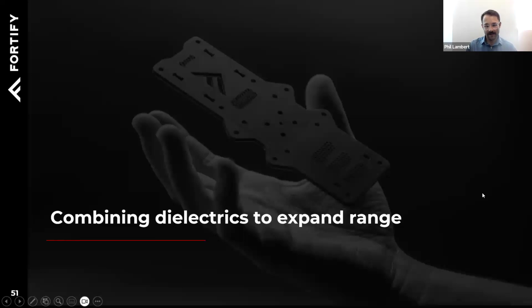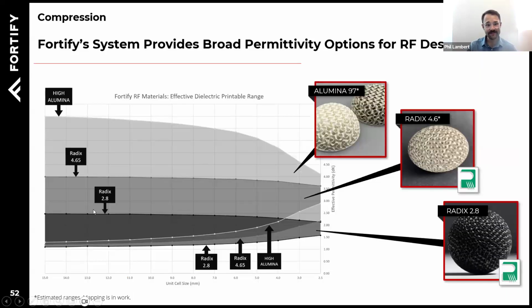Okay, so we talked about large lenses, but how do we go about combining different dielectrics to expand that dielectric range you can achieve within one device? And so you saw this chart a little bit earlier. Say if we wanted to take advantage of the Radix 2.8, which has a lowest dielectric constant as low as 1.2, but we also wanted to take advantage of the high alumina, which we know has an effective dielectric constant of around 5. The dielectric constant of the solid material is around 8, but we can achieve around 5 to 6 using our effective media approaches. And so that means we want to go from, say, 1.2 to 5. We can't do that in one material, so we have to start looking at hybrid designs.